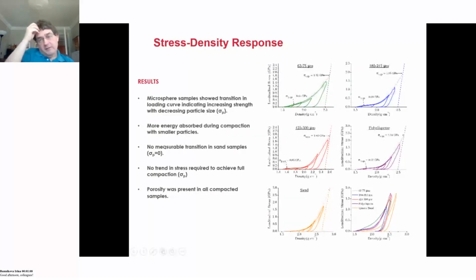So you can do a series of experiments using different particle sizes, and here is sand. Here is all the data put onto the same kind of curves, and so basically there is increasing strength with decreasing particle size. That's not a big surprise. You find that kind of analysis in many of the textbooks because critical flaw size, the number of flaws in these particles, etc., changes with dimension. You can have a particle that is so small it cannot break because, using the Griffith criterion, you find that you cannot get enough energy back to support that crack.